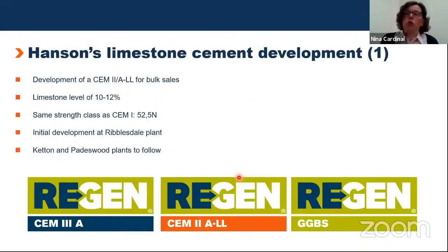What have Hanson done in order to prepare for this situation? We have developed a CEM II A-LL, a limestone cement, for bulk sales. It contains limestone levels around 10 to 12% at the moment, and I think the key is that it is the same strength class as our CEM I, our current Portland cement. It's a 52.5 N cement. We started this development at Ribblesdale, from where this cement is now commercially available already now, and our Ketton and Padeswood cement plants will follow very soon, still this year, with the same product offering. And you will probably see it branded as a REGEN CEM II A-LL.